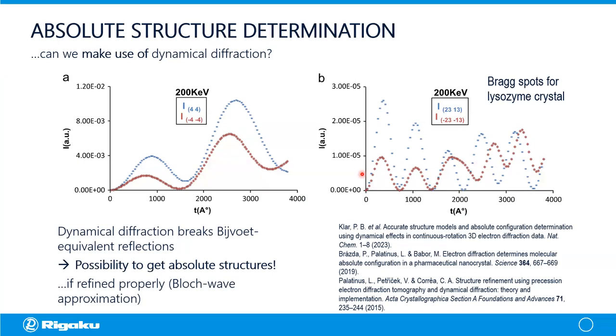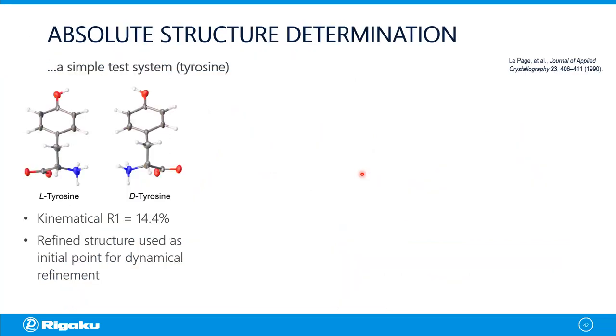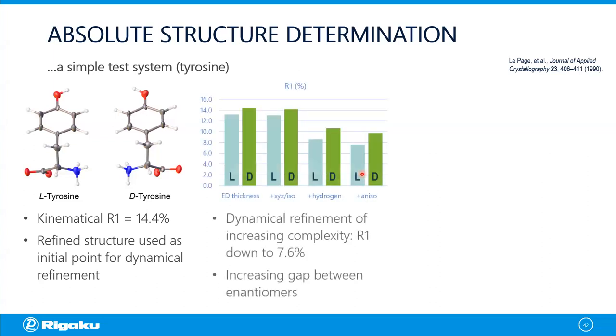In the case of PETS and Jana, we're doing a Bloch wave approximation. This has been published in the literature by the Palatinus group at the Czech Institute of Physics. So our test case has been L-tyrosine with kinematical refinement, that is, no consideration of dynamical diffraction. R1s are in the low teens. We use the kinematical refinement as a starting point. We then account for the thickness of the sample, and this reduces the R1. We then do an XYZ isotropic refinement, add hydrogens, and then do the anisotropic refinement. R1 drops down to 7.6%.